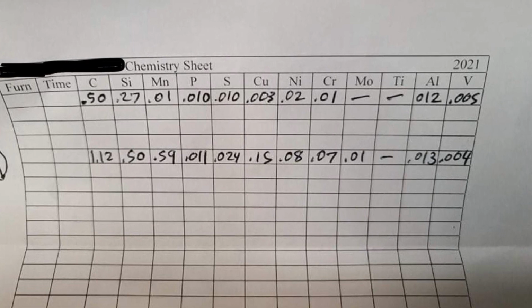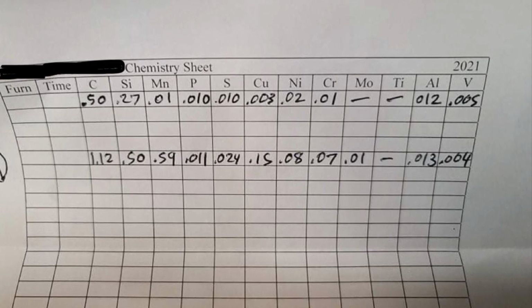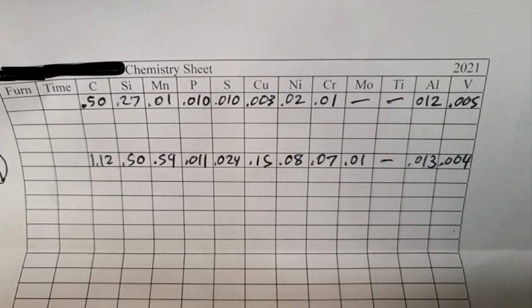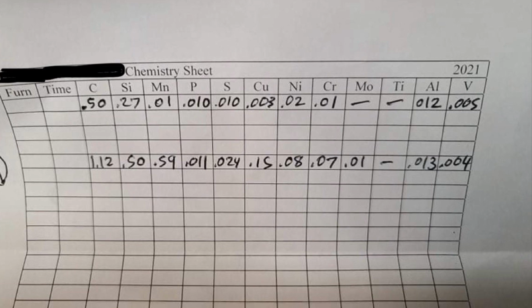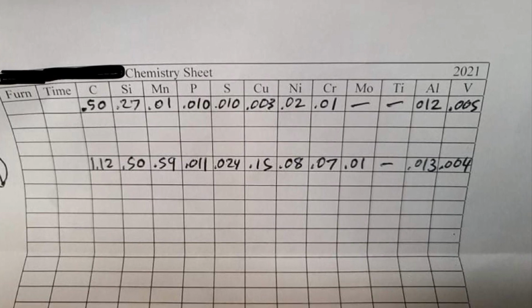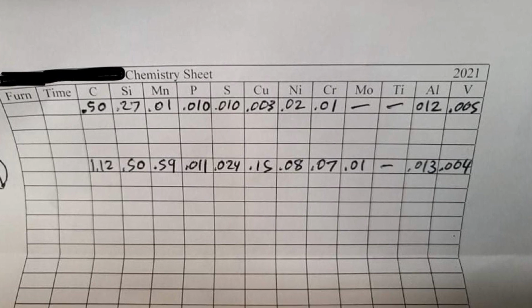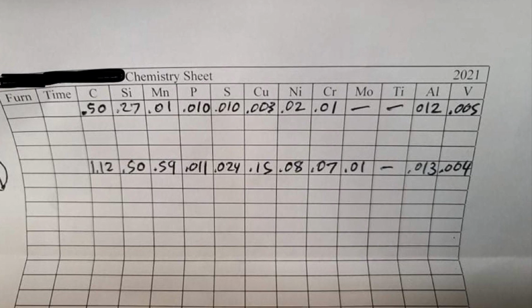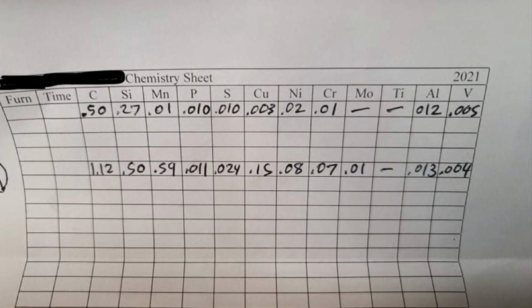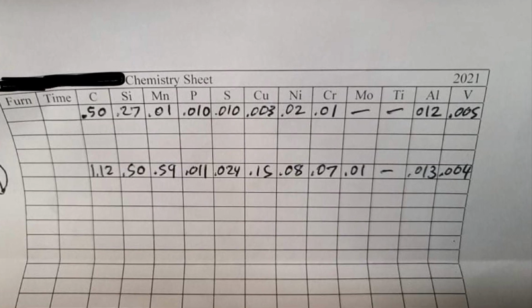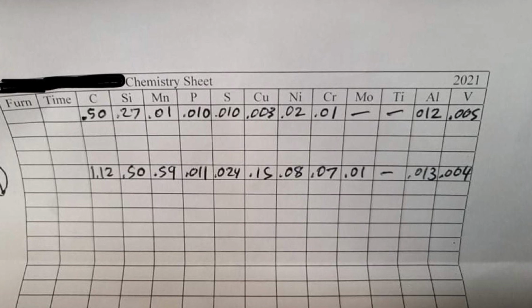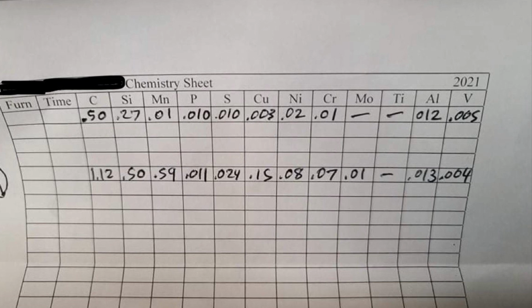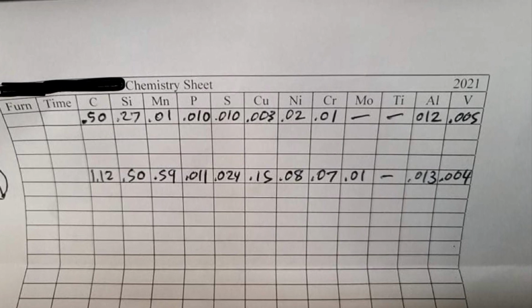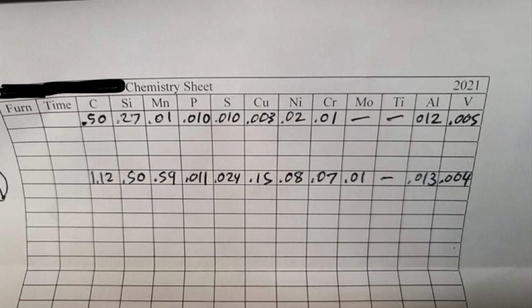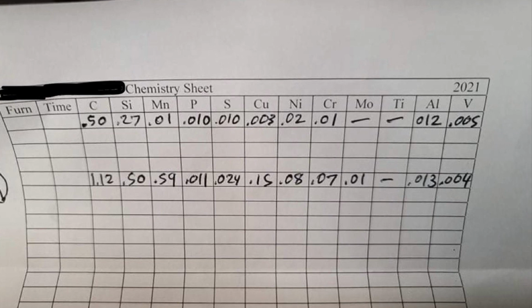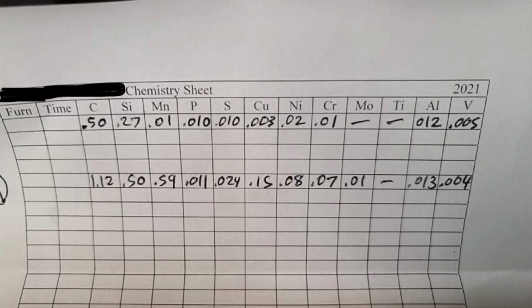But anyways, you can see that the manganese content is low, like I mentioned. And it's kind of interesting, the vanadium content, which I believe is right in the lines of historical Wootz. So that's kind of cool to see, and I'm wondering if that's coming from the sorrel, but I don't know. The bottom line is an ingot that was 1018 and graphite powder. And like I mentioned, you can lose some of your graphite powder in the slag, so that might be why the carbon content is so low in that ingot. And as you can see, using the 1018, the manganese content is high. But again, over here, it shows we have vanadium. So really interesting. It's good to have this kind of information so you can make adjustments. But yeah, kind of cool.